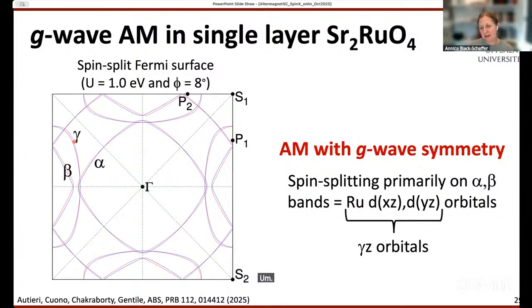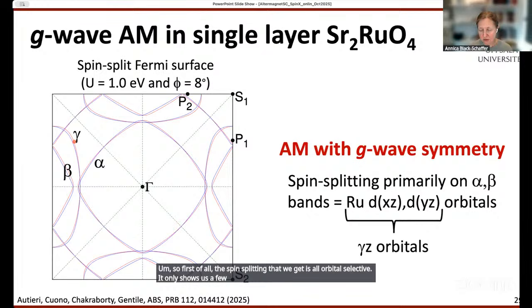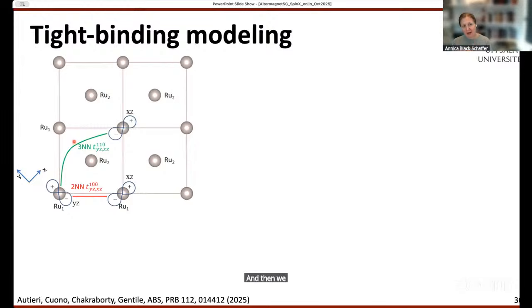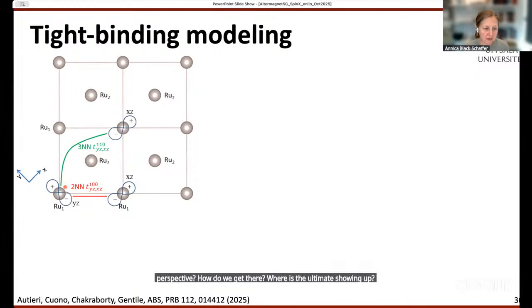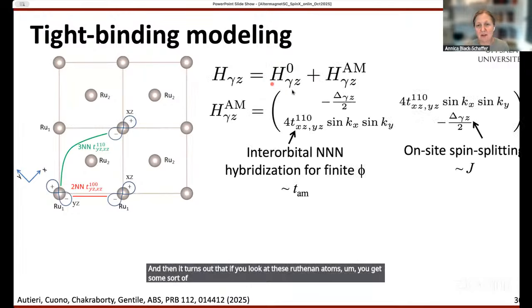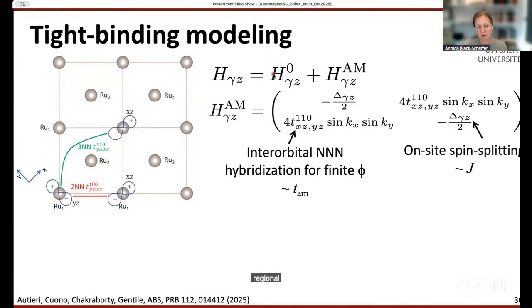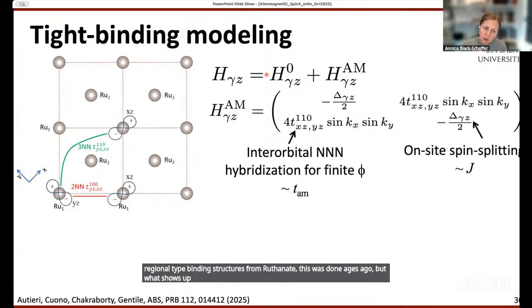So first of all, the spin splitting that we get is orbital selective. It only shows up on 2 of the 3 orbitals. And then we were asking, how can we understand this from a tight binding perspective? Where is the altermagnet showing up? It turns out that if you look at these ruthenium atoms, we have some original tight binding structures from ruthenate. This was done ages ago. But what shows up extra when you do this oxygen rotation is that you get a hopping between this orbital and this one. And you can understand that yourself.